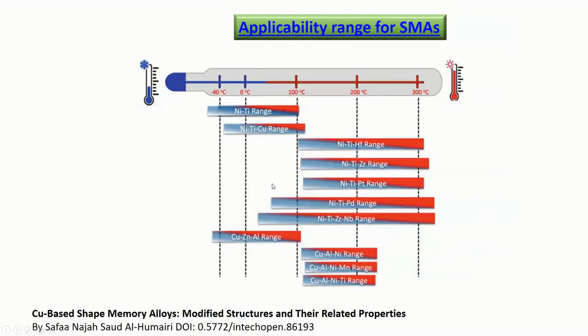So along with that, this is again a comparative chart for the temperature of interest. Okay, so at what temperature? So this alloy, as I have shown, is a magic alloy. It can remember its shape, that is fine, but this can happen only at some specified temperature range. And for the case of nickel titanium based alloy, we see that this temperature range is around minus 50 to plus 100 degrees centigrade. Okay, so quite related to the room temperature and a little bit on both the sides. We can still get a higher temperature range also in the nickel titanium by adding some hafnium, zirconium, platinum, etc. And for copper base, we are having this temperature within 100 to 250 degrees centigrade or so on.